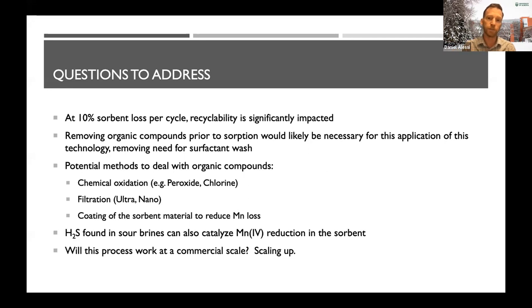The reduction of manganese. Of course, when you put a barrier on something, it's going to reduce either the amount of lithium that can be taken up by the material or how fast the lithium is taken up. But the question is whether this is a worthwhile exchange, right? We lose a little bit in the rate or extent of recovery, but the synthetic mineral lasts longer. And that's really the point of this project that we have going.